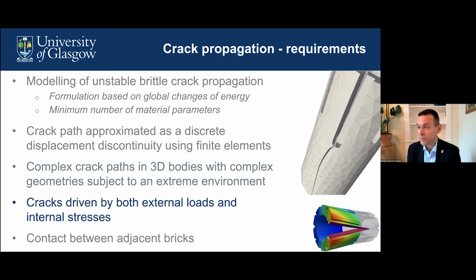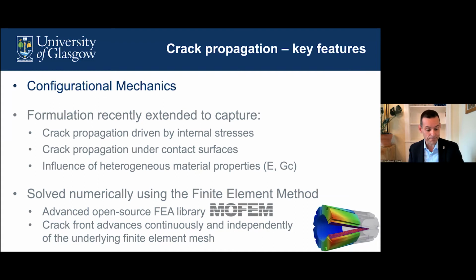Perhaps most critically, one of the biggest challenges we faced is that the cracks that we have observed are largely driven by the complex internal stress state, not just by any external loads that are applied. It is the changing internal stress state combined with the changing material properties that is thought to be the cause of these cracks. The additional complexity is that we also have contact between interacting bricks, and that's another issue that I'll hopefully get a chance to briefly talk about.